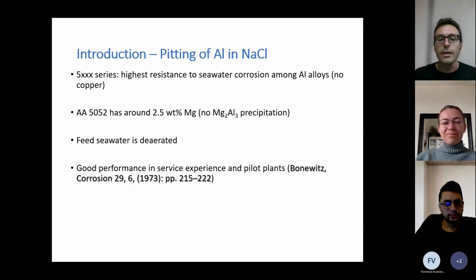It has a lower amount of magnesium compared to alloy 5083, which has a higher strength. The lower amount of magnesium means this precipitate doesn't form, and that's good news because that precipitate, in some cases, causes intergranular corrosion. The feed seawater was going to be deaerated. That is good news for aluminum.